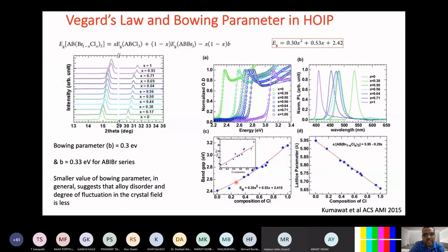So MAPbBr3 and MAPbCl3, both of them have the cubic crystal structure, and hence by mixing bromine and chlorine in the various compounds, you see your lattice constant just follows a straight line. That was an amazing result. I was very happy to see that there is no change. The lattice constant is just following a single straight line. There is no in-between change in the lattice structure. And you use Vegard's law, and you fit your experimental band gap from the UV-vis data with respect to the chlorine composition, and you determine your bowing parameter, which is basically the x squared term, and it is 0.3.